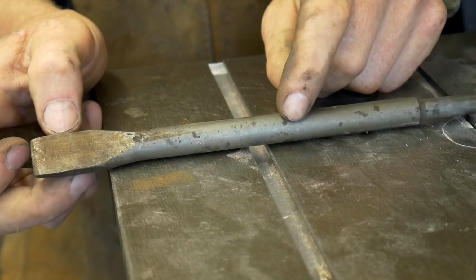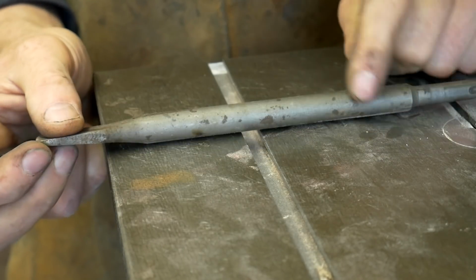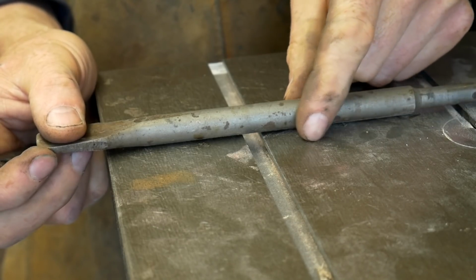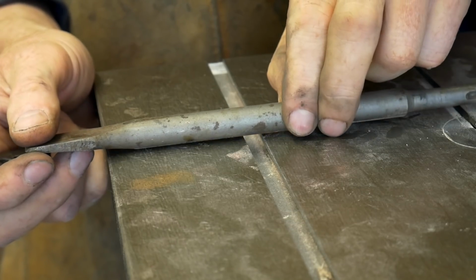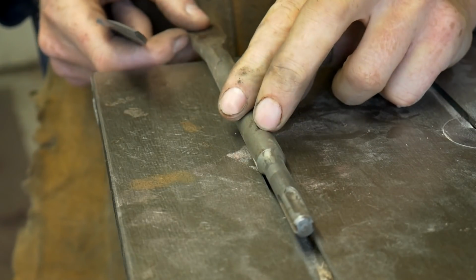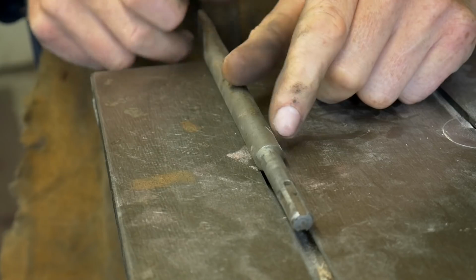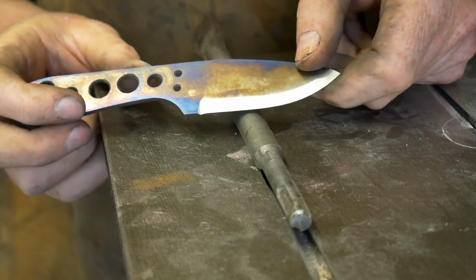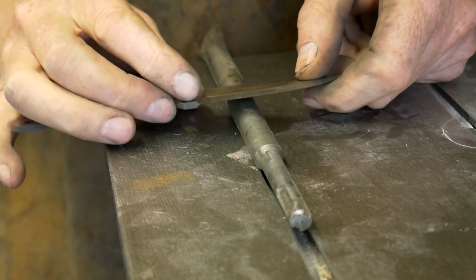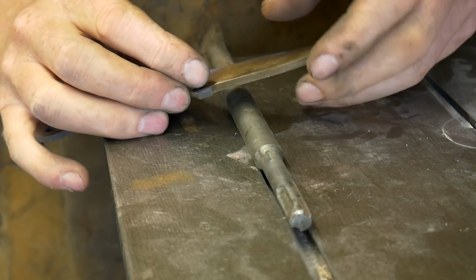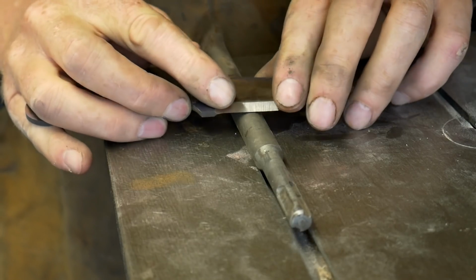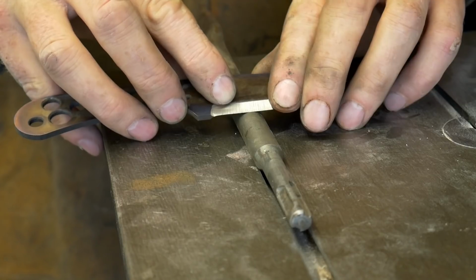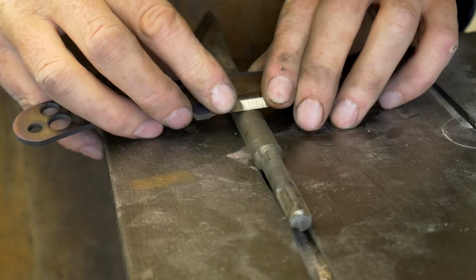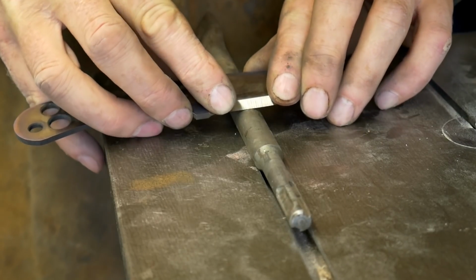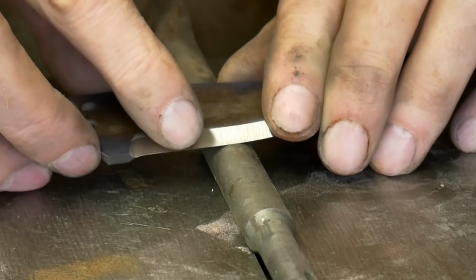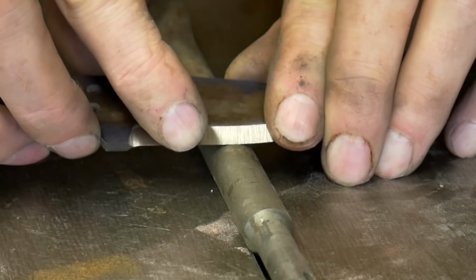Here's a piece of, it's actually a cold chisel, but it's very hard steel, and it's got a circumference. It's about 3/4 of an inch in diameter. There's a knife bevel, very coarsely ground rough bevel, and I've stropped it just to remove the wire edge, the burr, and I can rest the bevel on at the bevel angle, and then apply a bit of pressure and see the bevel deflecting. And then I can see it bouncing back.